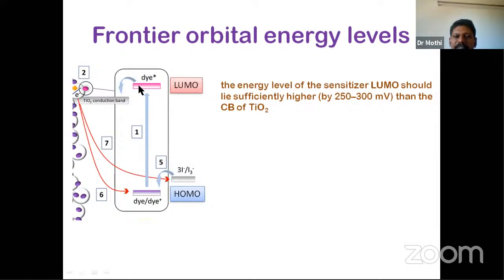If you can see here, the red box that corresponds to LUMO, this energy level should lie sufficiently higher than the conduction band of TiO2, because only then the electron can be efficiently injected. Otherwise, if the conduction band lies above the LUMO, the energetics will not be favorable.